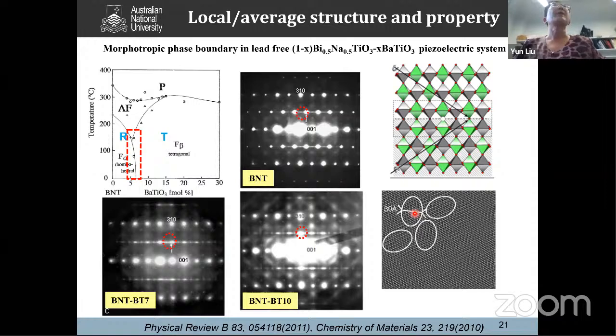Okay, so that's what we found: in these materials, under the umbrella of the average structure, you have the local structure that came from the octahedral tilting. With increasing concentration in that range, you will find that this half 111 satellite diffraction becomes weaker. This half 110 becomes stronger. So that indicates this kind of stacking fault generated, induced the local structure gradually grew in length, in size, and in correlation length.